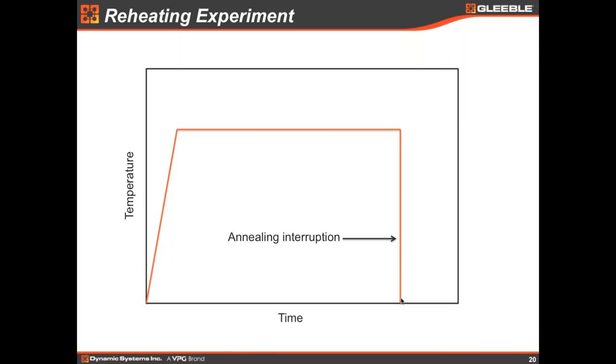When you're reheating a slab, of course, the slab is a massive piece of metal, and you have different heating rates in the center and at the surface, and also different plateaus, but we can actually do exactly what happens for that specific point. So you cannot simulate the whole reheating process in all areas of the slab, but you can perform the simulation for specific or discrete points that you select. At the surface there is one heating rate and one thermal cycle. In the center there is another thermal cycle. So you can simulate both.